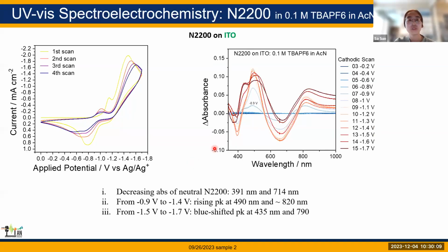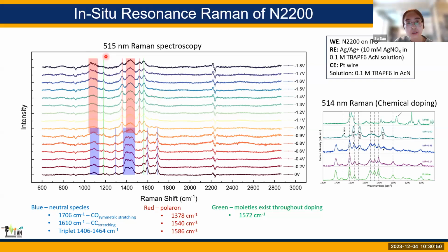So with that, let's move to the N2200 on ITO, but measured in non-aqueous solution. This experiment is done in acetonitrile, and we can see similar two reduction peaks. From the potential-dependent absorption spectra, we can also see what the previous literature reported: the two absorption peaks growing for the monopolaron and the shoulder for the bipolaron. We also use 515 nanometer Raman, which is more resonant with the polaron structure.